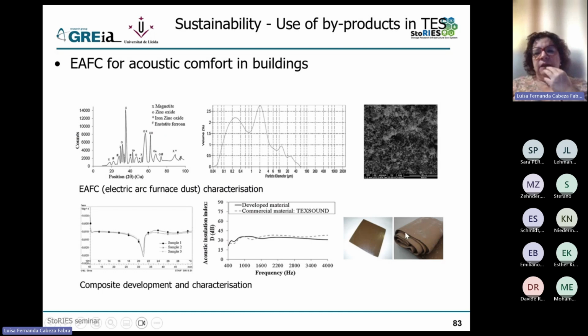And we produced this new material that we characterized a lot. Here again, talking about materials, there was a challenge on how to characterize this polymer. You can take a small sample and put it in the DSC, but since the amount of PCM is small compared to the material itself, and the polymer would not go through phase change in the temperatures we were testing, there was a challenge on how to use it, and we developed a full method with our DSC to be able to produce this figure that you see in the left bottom side.